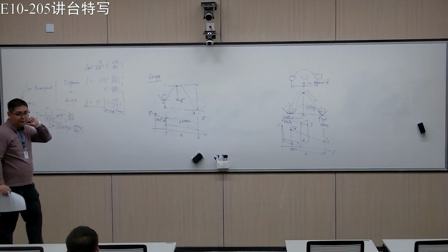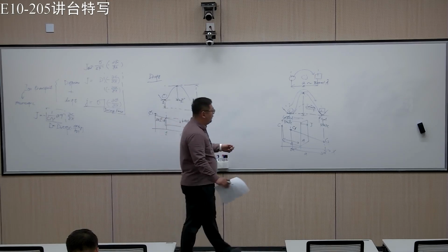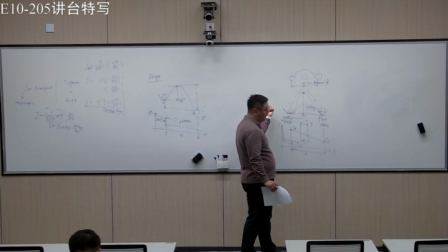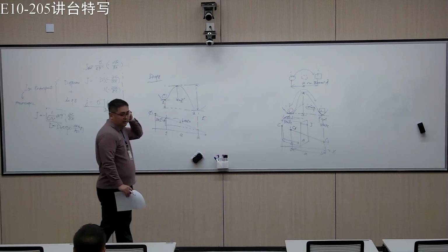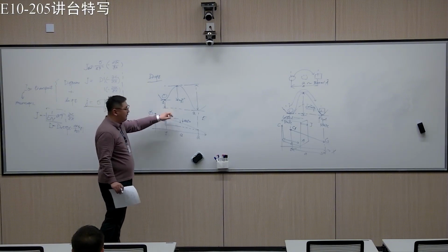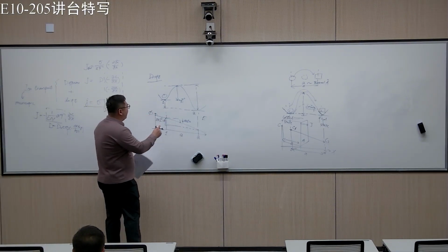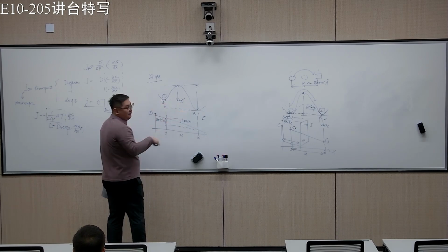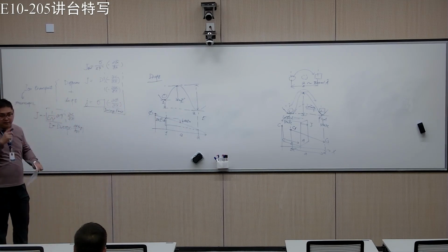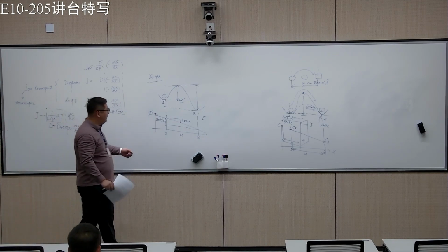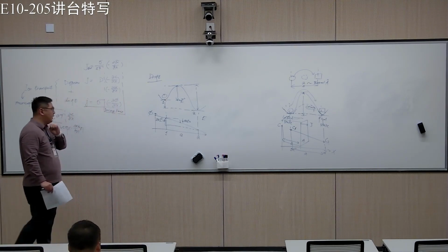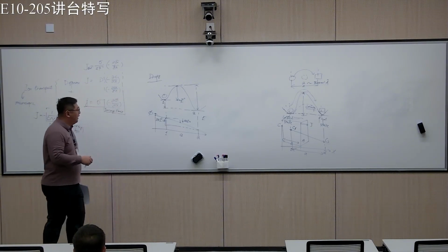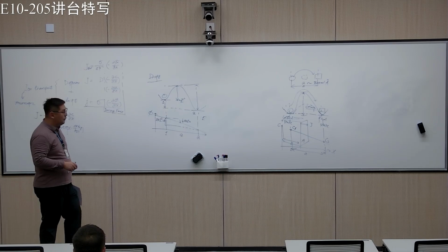So that's why drift is different from diffusion. For diffusion, the ion can jump from here to here, or from here to here, with the same probability. However, for drift, it's directional. If I apply an electric field, and we talk about cations, then they will definitely go that way. That's how you have the current.